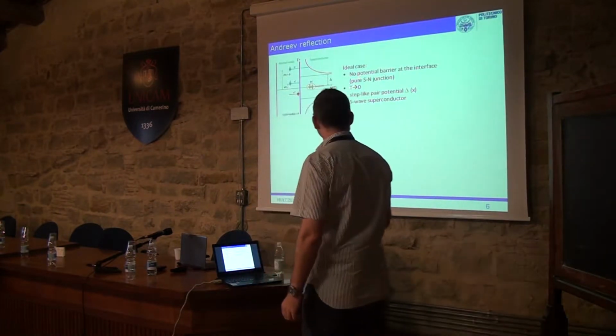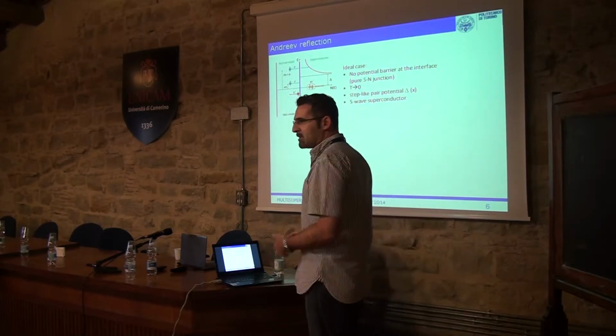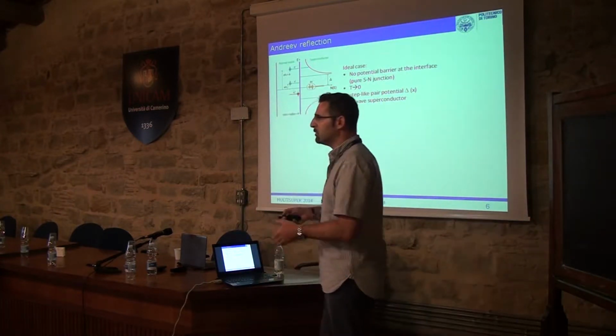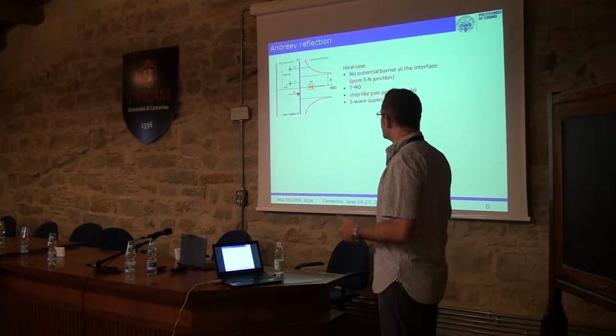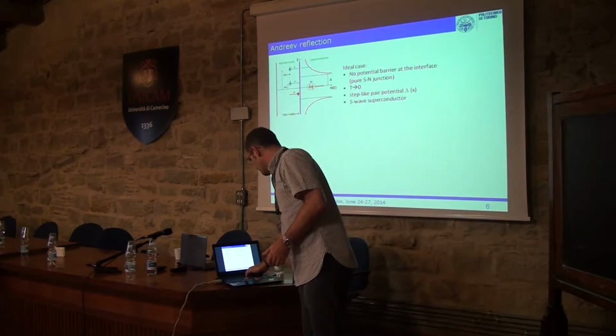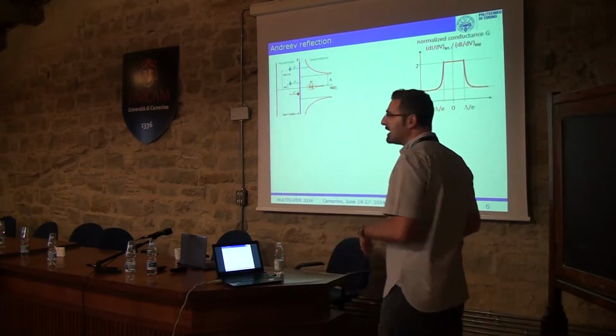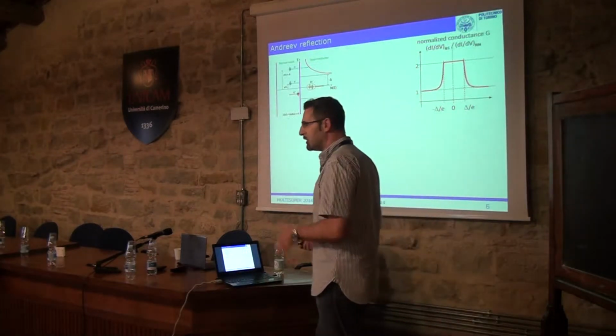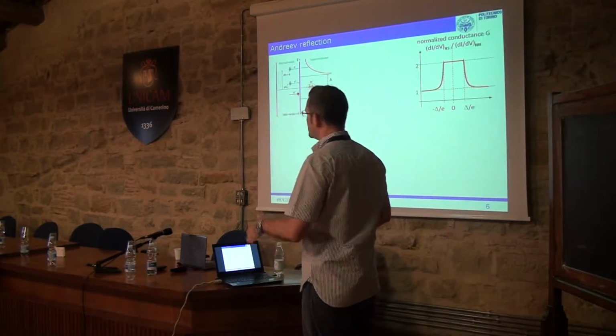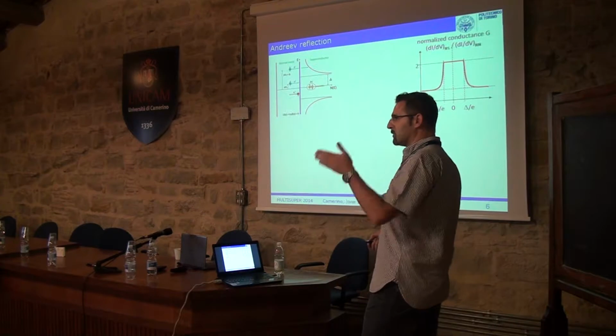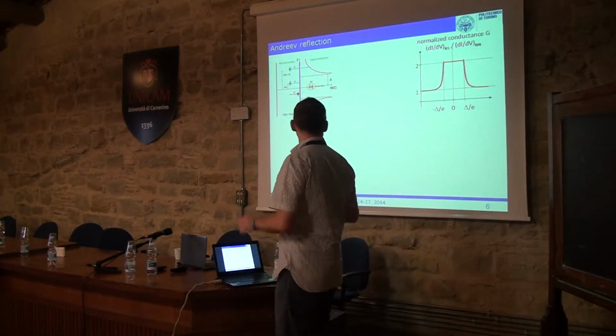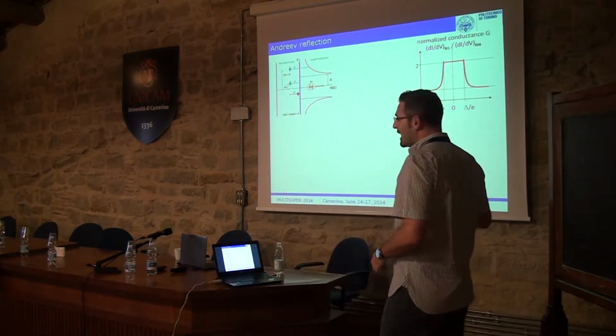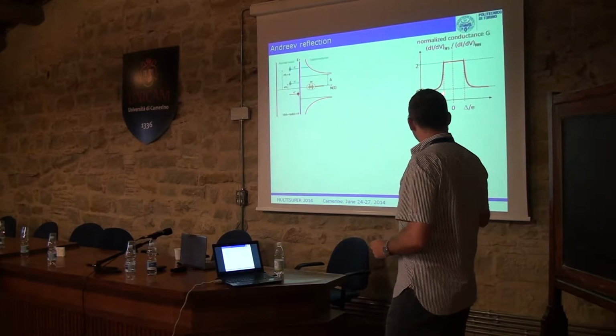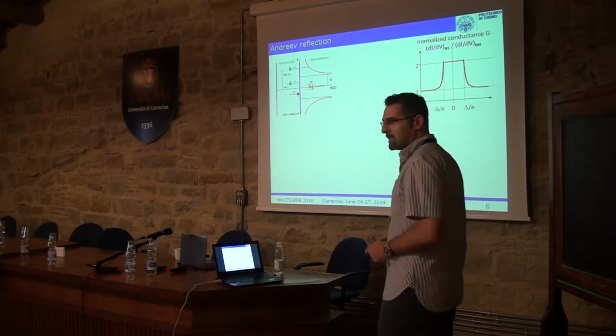Well, Andreev reflection is, of course, the mechanism that allows point contact to measure the gap. I will skip the details. The important thing from our point of view is that in the very ideal case, where we have one-directional injection, an s-wave superconductor, T equal to 0, and so on, we expect a doubling of the conductance of the junction in an energy range between minus delta and plus delta.